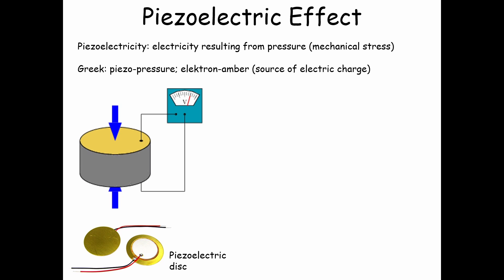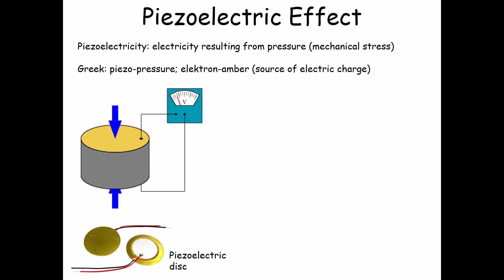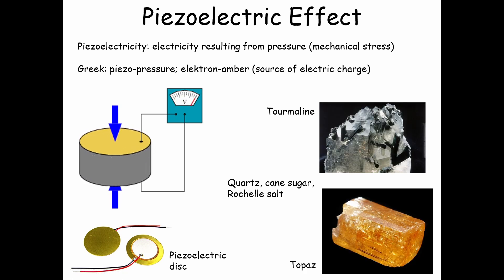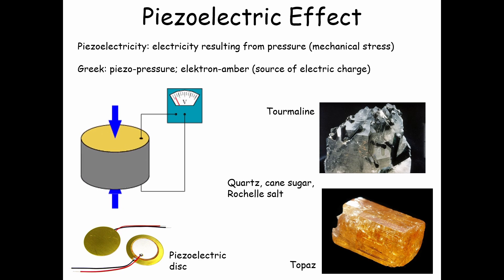This animation shows the application of pressure, which leads to the generation of voltage, which can be seen in this voltmeter. Piezo materials can be synthesized in the form of discs, plates, rings, and cylinders, and piezo discs are one of the most widely available commercial products. Piezoelectric effect is demonstrated by crystals which do not have a center of inversion. Some examples include tourmaline, quartz, and topaz.